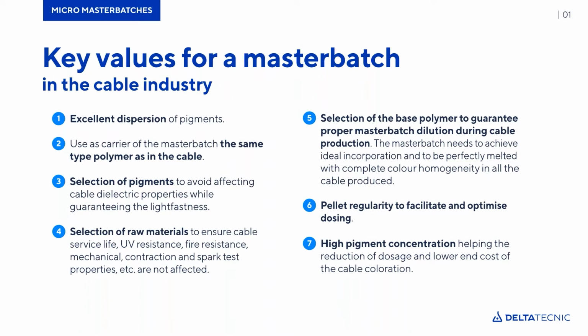And at the end, there is the point of the high pigment concentration. This is a critical point, I think. The higher the concentration of pigment inside a Masterbatch formulation, the more cost-effective the usage of that Masterbatch is, because at the end, the higher the portion of pigments in the formulation of the Masterbatch, the lower the dosage at the cable manufacturing process. Therefore, there is a clear saving in terms of quantity of Masterbatch purchased and used.